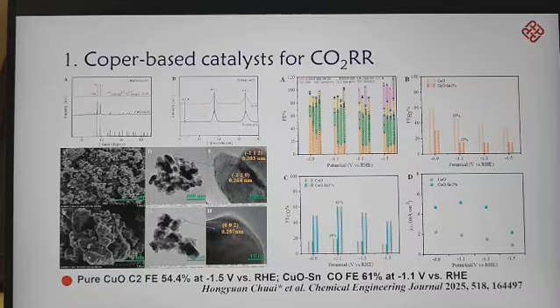XRD data showed that tin did not dope into the copper oxide lattice, and tin may be highly dispersed on the surface of copper oxide. SEM images reveal that pure copper oxide formed uniform particles, while tin-modified copper oxide aggregated into block-like structures.